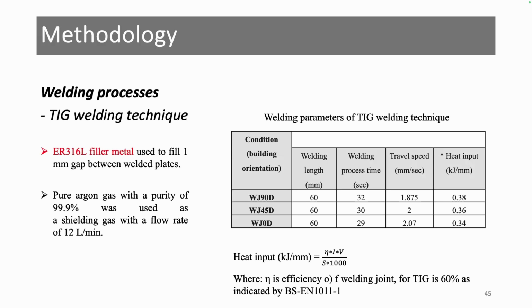For the TIG welding technique, we used filler metal 316L to fill the 1 millimeter gap between the base metals, and pure argon was used as the shielding gas. Regarding the heat input, there were some little differences. For the WJ90D, it was 0.38, here 0.36, and here 0.34 kilojoule per millimeter. So we consider that this is not a big difference in the heat input.